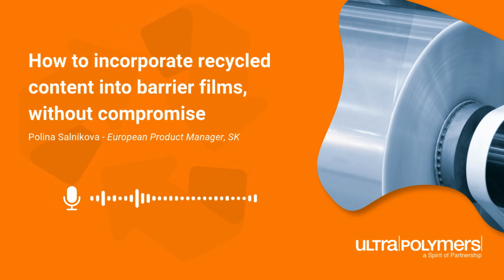Case study insight. Maintaining film quality at 30% recycled content. In this example, what the customer needed was a solution to produce a multi-layer barrier film with recycled content. Through incorporating recycled material, there could be no compromise in mechanical strength, barrier performance, or optical quality. Plus, the material had to be easy to incorporate into an existing industrial 9-layer blown film extrusion line.